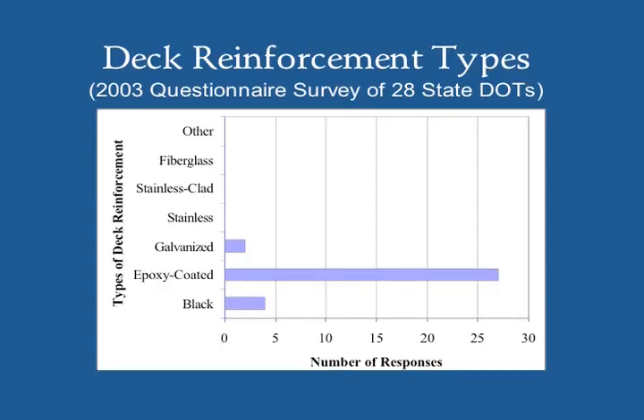To answer this question, let's talk about the type of reinforcement that's available. Again, these are results from the questionnaire survey of several state DOTs. You see that many DOTs use epoxy-coated rebar. This is commonly recognized by its green color. As long as the epoxy coating is intact, that is, no defects, no holes, no scrapes, the epoxy will prevent the chlorides from coming into direct contact with the steel and thus prevent corrosion altogether.